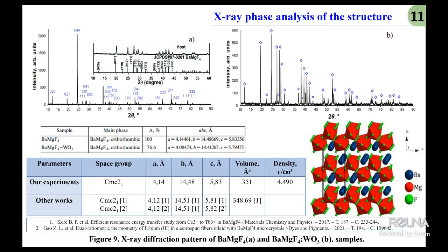The comparative data indicate a high degree of structural ordering in the obtained ceramics. The crystallite size was approximately 41 nanometers. Phase analysis confirms the exceptional phase purity and the homogeneity of the synthesized samples. These results confirm the successful synthesis of tungsten-activated BaMgF4 ceramics obtained via radiation synthesis without the addition of foreign substances, and the activator's incorporation into the crystal lattice.